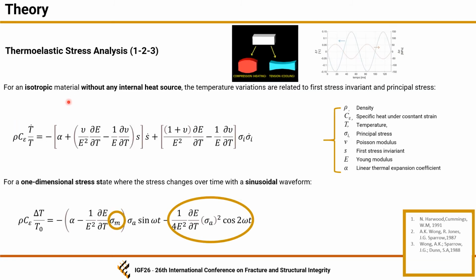Thermoelastic effect relates the temperature change with the change in the sum of principal stresses for an isotropic material under linear elastic and adiabatic conditions. The thermoelastic equation was derived by imposing the conservation laws which govern the mechanics of small quasi-static deformation and the second law of thermodynamics. We can see that the time derivative of the temperature is a function of the first stress invariant and the principal stresses, and by also considering a one-dimensional stress state where the stress changes over